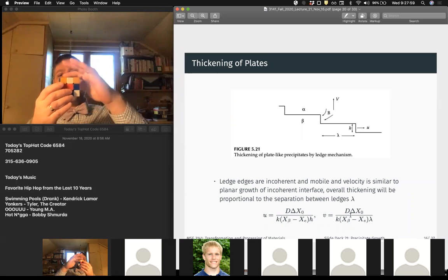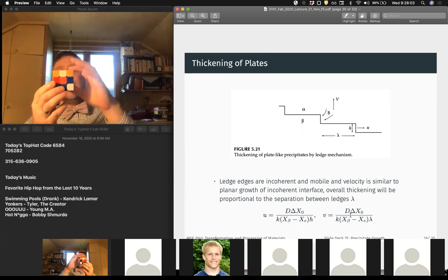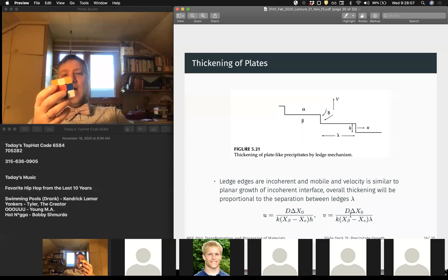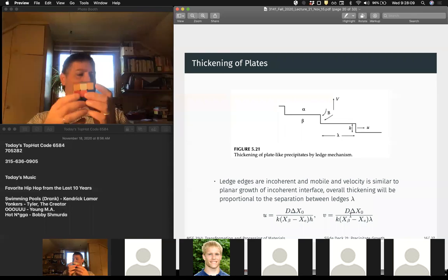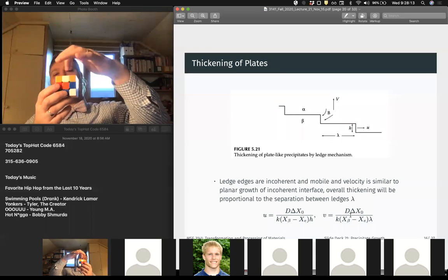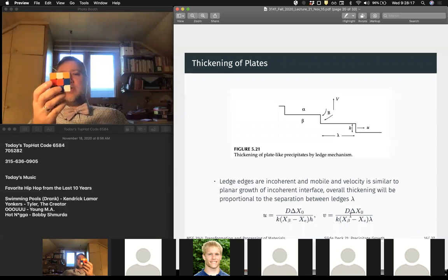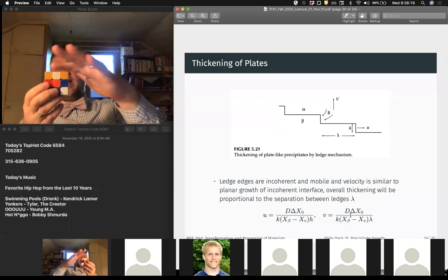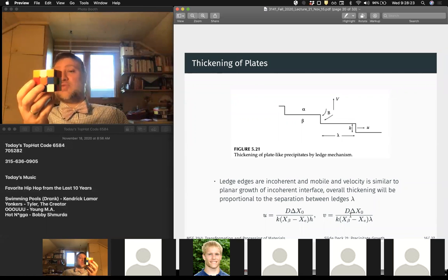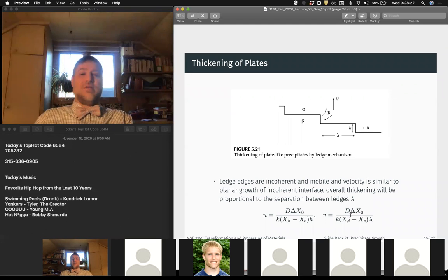The free volume associated with the coherent interface is very small, right? The growth rate is very slow. Because anytime I put another cube up here, I'm adding a very large energy penalty, right? I have to disrupt this perfect interface in a significant way.